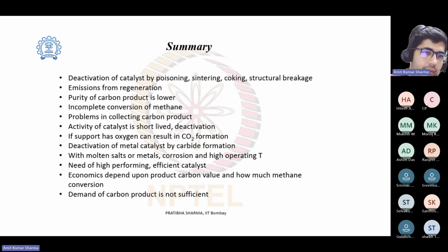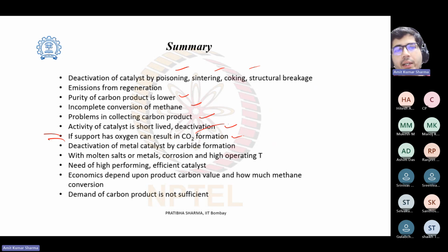So in summary, the deactivation is caused by poisoning, sintering, coking. Purity of carbon powder is lower, there is incomplete conversion, problems in collecting carbon product, activity of catalyst is short-lived, and deactivation is there. If the support has oxygen, it can result in CO2 formation, because we have seen the support can be aluminum oxide, zinc oxide. So if there is oxygen, it can also result in CO2 formation. Deactivation of metal catalyst occurs by carbide formation, molten salt or metals, corrosion and high operating temperature.